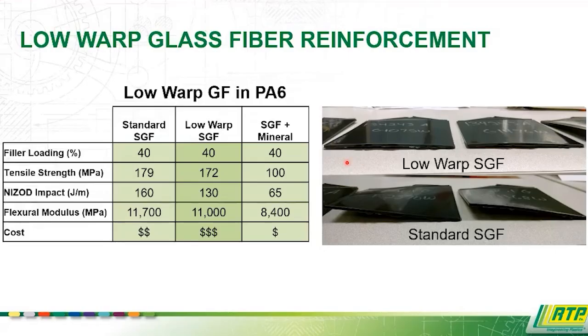These plaques over here are actually from my R&D days. I did a study using this low warp glass fiber technology where I could drop in back-to-back lots of 40% nylon 6, and the standard chips, these are 6x6 plaques. The standard plaques would come out all warped and potato chipped, move back to that low warp short glass fiber, and back to flat again. It was really pretty amazing. The downside is you do pay extra for that. So not necessarily a go-to technology for high volume applications, but if you're really sensitive to dimensional stability and you need all the strength you can get with the glass fiber, it is a good, interesting option for that.